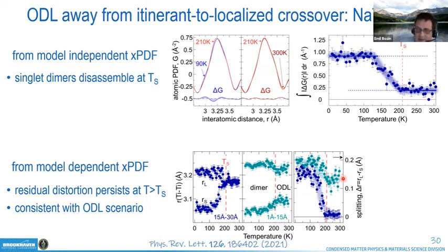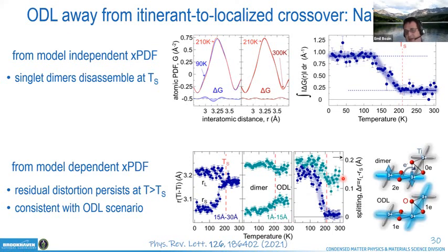So given that this is a titanium-containing system where titanium is in a d1 state, this is very similar to a spinel system with titanium that I mentioned before, in which this type of behavior is understood by the following cartoon, in which you have at low temperature, locally, a dimer state, which has a strong covalent bond with 2 electrons in it.